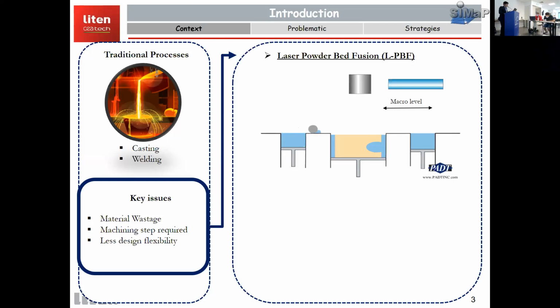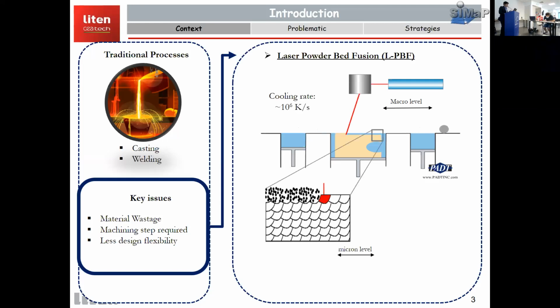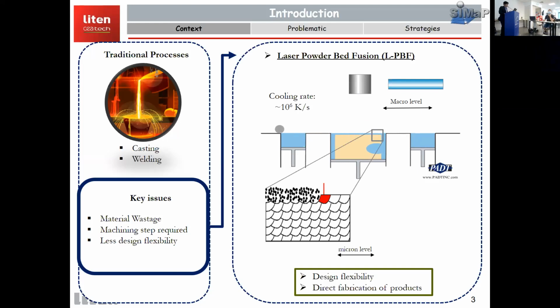So with the laser, basically you are melting the powder material, and due to the rapid solidification at very high cooling rates, for example 10⁶ Kelvin per second, you end up having very fine micro level melt pools, which leads to design flexibility with this process, and you can end up getting direct fabrication of products.